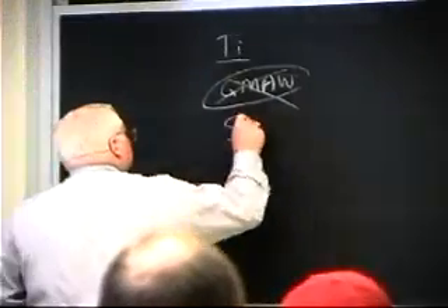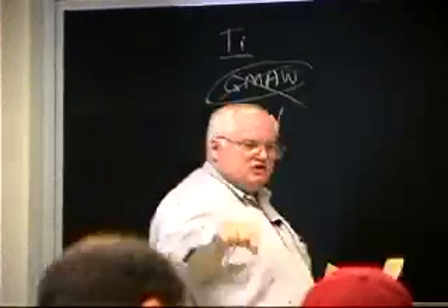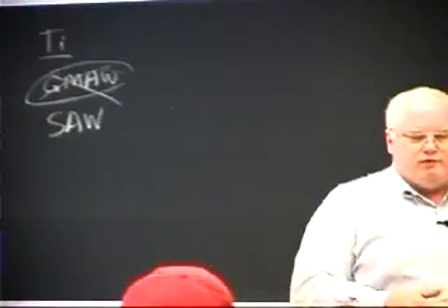The Navy did a lot of research on it, and in the laboratory they could make nice small plates and get good welds, but if you ever try to make a 10-foot weld or something like that, there's all kinds of defects. It basically is an unstable arc. And we don't have to go into too much of that. Of course, the other thing we use with steel is submerged arc welding, where you have this granular flux you pour over the surface. And it turns out the very first contract I ever had back in 1977 was to submerged arc weld titanium from the Office of Naval Research. And this is one of those welds.